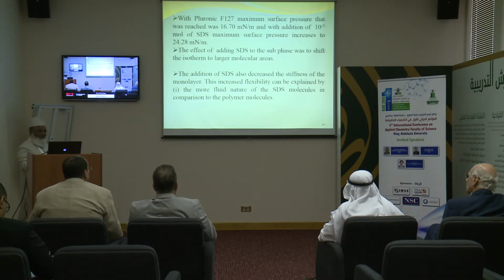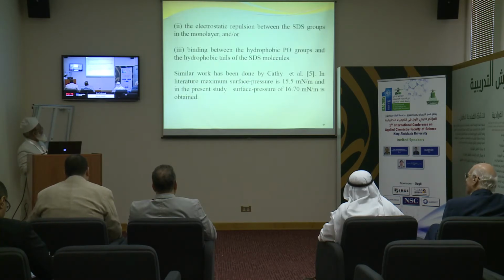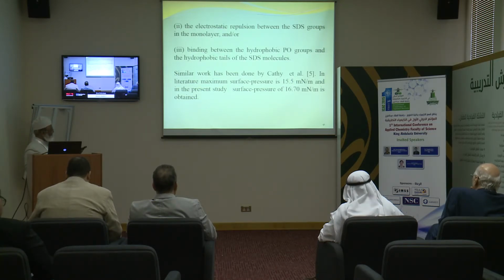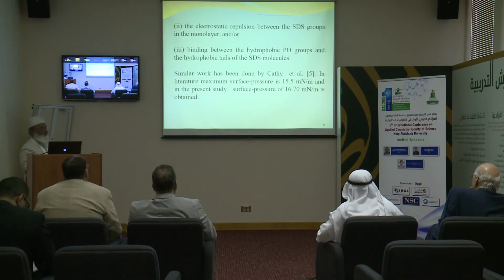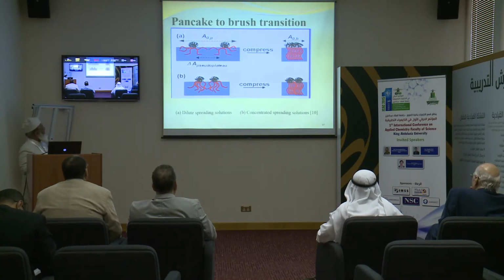This increased flexibility can be explained either by the more fluid nature of the SDS molecules in comparison to the polymer molecules, and the electrostatic repulsion between the surfactant groups in the monolayer, or binding between the hydrophobic PO groups and the hydrophobic tails of the surfactant molecules. Similar work has been reported in the literature, and they have reported the surface pressure values as 15.5, whereas in my work we are getting 16.7, which is quite comparable to that reported in the literature.